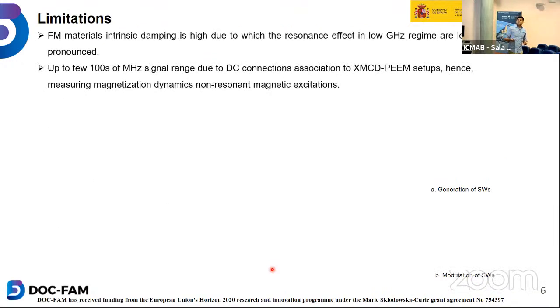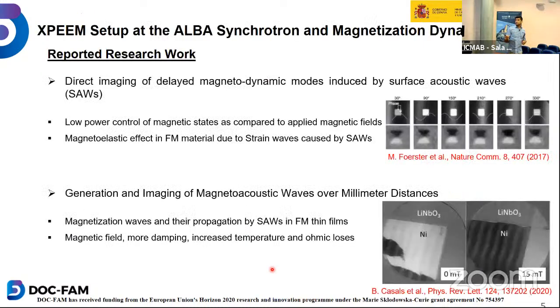The limitation that was already there is that ferromaterials usually have intrinsic damping. In the previous experiment, they used 500 megahertz frequencies. They excited the sample at 500 megahertz through IDTs, which generates a surface acoustic wave in the lithium niobate, which is piezoelectric, and that generates the spin waves. But its range is quite small, up to 15 or 25 millimeters, as recorded. We want to increase this limit.